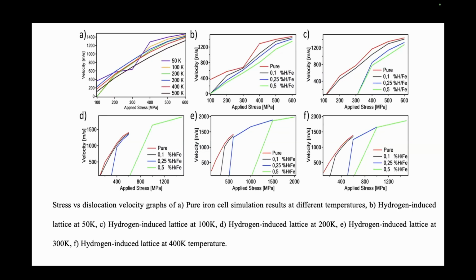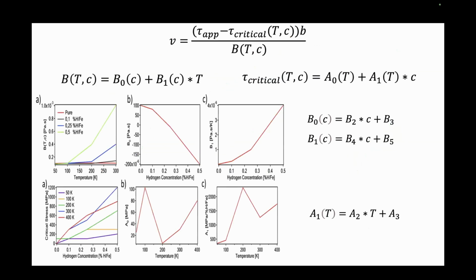And these are the stress versus velocity graphs of pure iron and hydrogen-charged lattice at 50, 100, 200, 300, and 400 Kelvin. Mostly, once we increase the hydrogen concentration, we are impeding the dislocation. We are slowing down the dislocation, decreasing its velocity. Then the next step is to derive the mobility laws. Here in our calculations, the velocity is tau applied minus tau critical, the critical stress that activates the motion of dislocation, times the Burgers vector divided by the drag coefficient. But here, the drag coefficient is not only a function of temperature, but also of hydrogen concentration.